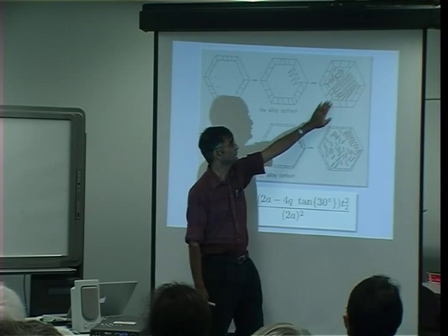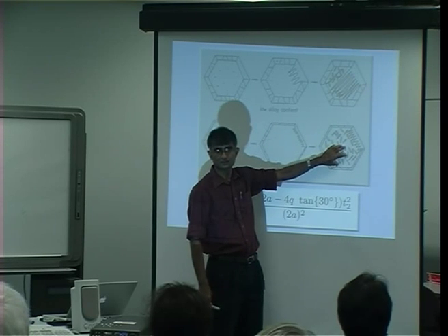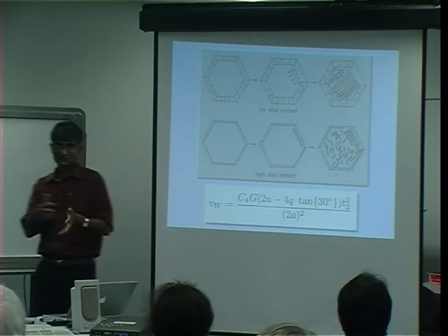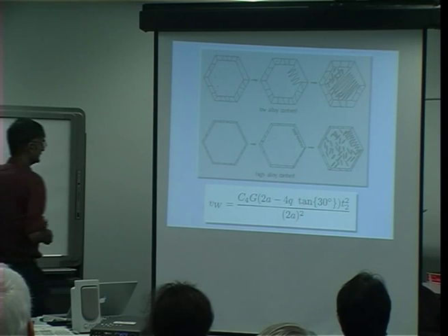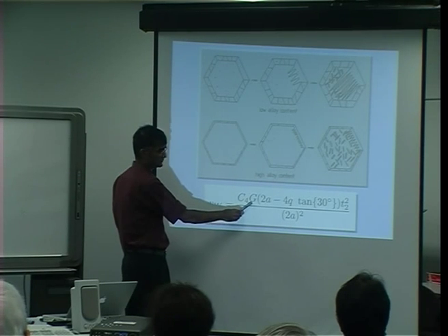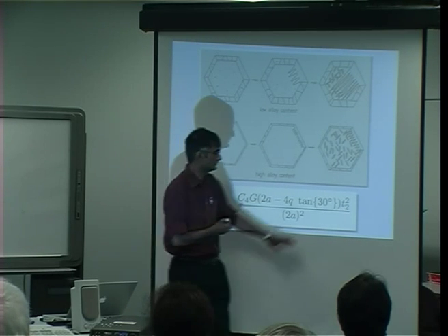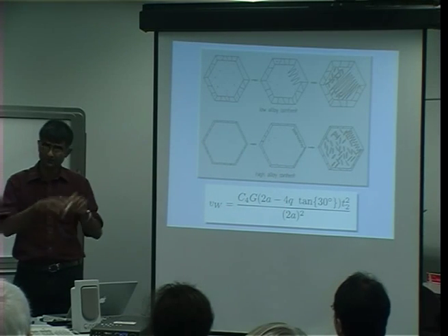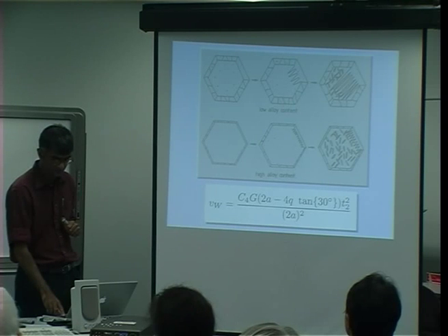In this case, it's so fast that it spreads across the grain before there is an opportunity for much of the acicular ferrite to form. Whereas in this case, because the growth rate here is slow, the acicular ferrite can dominate the microstructure. Okay? So we need to take account of impingement between particles growing from different regions. So when we calculate the volume fraction of Widmanstätten ferrite, it's not just a function of the growth rate, but also of the austenite grain shape and size, and the time taken to get impingement between intragranularly nucleated plates and those forming from the grain boundary. So I'll show you later on that when we take this into account, we get good agreement between the volume fractions.